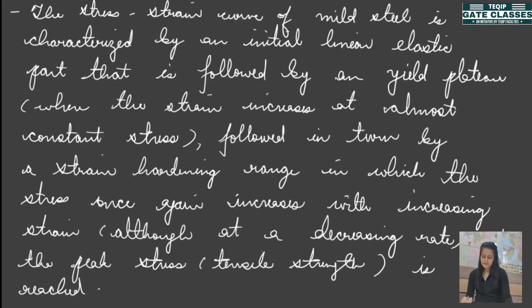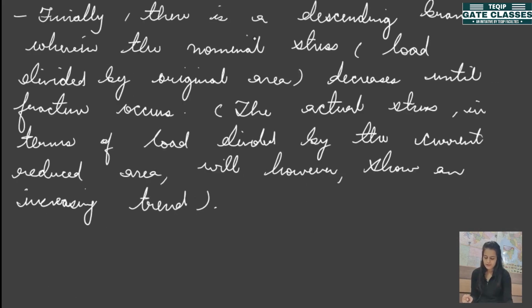Okay, so the stress strain curve of mild steel is characterized by an initial linear elastic part that is followed by a yield plateau where the strain increases at almost constant stress, followed in turn by a strain hardening range in which the stress once again increases with increasing strain, although at a decreasing rate until the peak stress, that is tensile strength, is reached. Then finally there is a descending branch wherein the nominal stress, that is load divided by the original area, decreases until fracture occurs. The actual stress in terms of load divided by the current reduced area will however show an increasing trend. Okay, तो डिसेंडिंग जो ब्रांच होती है वहां पर हम नॉमिनल स्ट्रेस को लेकर चलते हैं एंड नॉमिनल स्ट्रेस इज द लोड डिवाइडेड बाय ओरिजिनल एरिया, so that will show a decreasing trend. But if we talk about the actual stress, which is the load divided by actual current reduced area, then it will show an increasing trend, right?